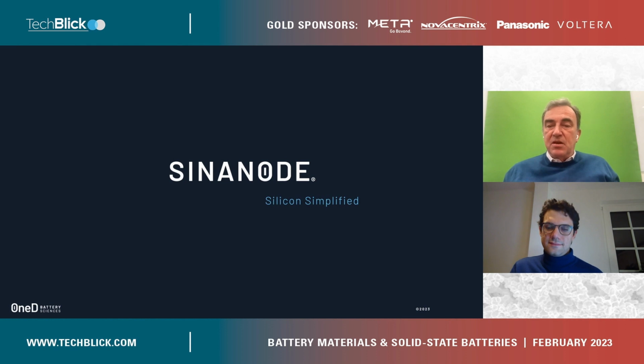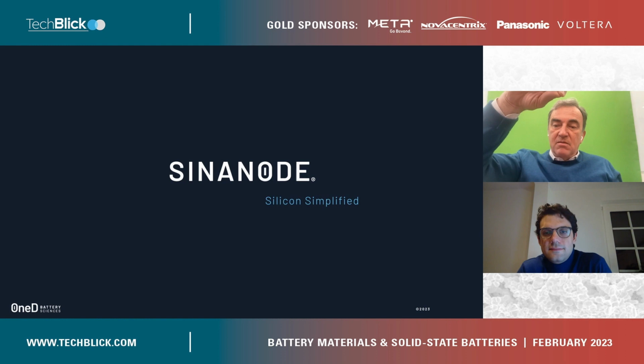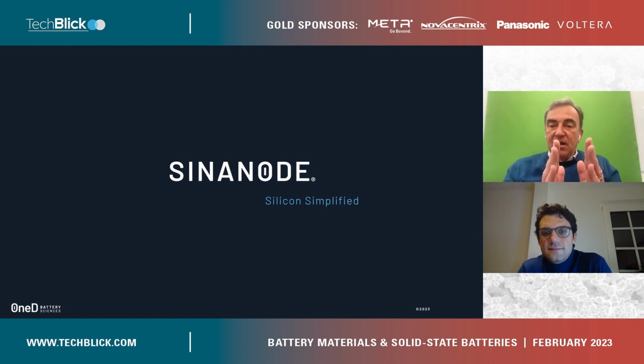basically becomes supersaturated copper silicide, and then the particle deposits the silicon atoms like layers, and the little copper catalyst grows and is at the tip of the nanowire. The diameter of the nanowire is set by the diameter of the copper catalyst. This is kind of crazy because it happens very quickly. In less than an hour, you can grow micron-size nanowires, hundreds of thousands of nanowires per particle of graphite. So it's very fast, and they grow in those various ways.